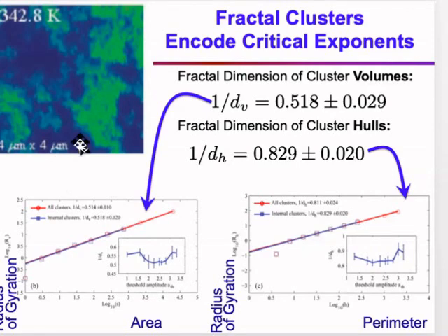Another one that's very natural is to study the fractal dimensions of the clusters. As you can see, this green cluster here, for example, isn't compact. It's not all green on the inside. There are regions inside of it that are blue. And its boundary is not compact. It has a rather intricate boundary. So we can encapsulate both of those geometric properties with a critical exponent.